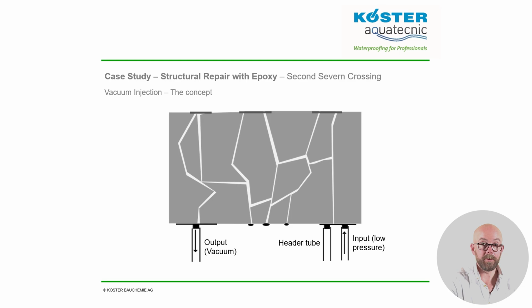The vacuum pump gently removes air and residual moisture from the crack network, creating a low-pressure area which is then ready to receive the injection resin. At this point, the inlet valve was opened and the resin released. A slight positive pressure was also applied on the injection side as this sped up the process. The resin flowed very easily into even the smallest of cracks and filled the header tube, which was fixed at an upright position.